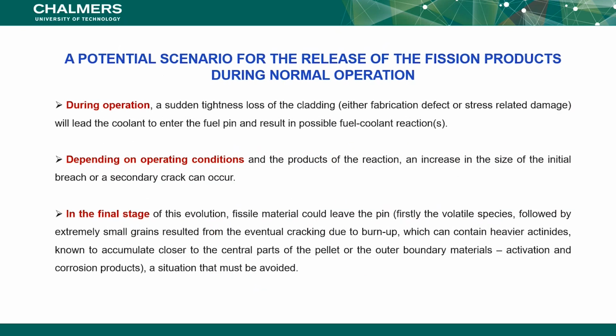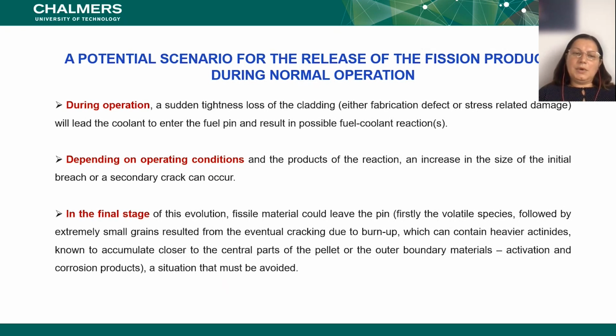So when something happens, what can happen? Well, a lot can happen, but when you take it down to the fuel during operation, you can have a sudden tightness loss of the cladding. So as I said, you have potential defects, or you can have stress-related damages. And this will lead first, well, here it says that it will lead the coolant to enter the pin, but first you will have a very small pore, and that pore will probably make it easy for the coolant to try to enter the pin. And the result can be a possible fuel coolant interaction. So the coolant will come from the outside and interact with the fuel inside.